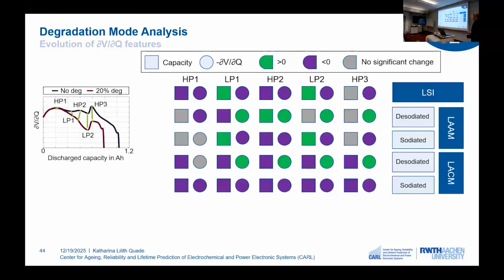And we can see again very distinct patterns, especially when we look at HP3, which has the highest variability over aging. We can see that for loss of active anode material and loss of active cathode material in the desodiated states, this peak shifts upward, and for all other categories, it shifts downward.